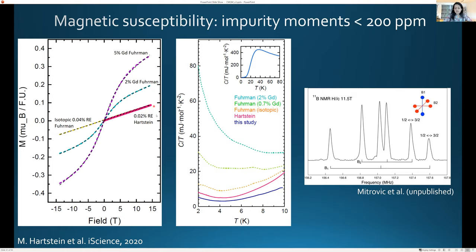We can put an upper bound of 0.02% on the rare earth contribution, and it's basically the same as an isotopically pure samarium hexaboride with no rare earth inclusions. It was also shown in the same study that when there's doping of gadolinium, the heat capacity goes up substantially, whereas we show that the crystals that we measure have a low but finite linear heat capacity of about 2 millijoules per mole Kelvin squared, which is even lower than the isotopic materials measured by the group.